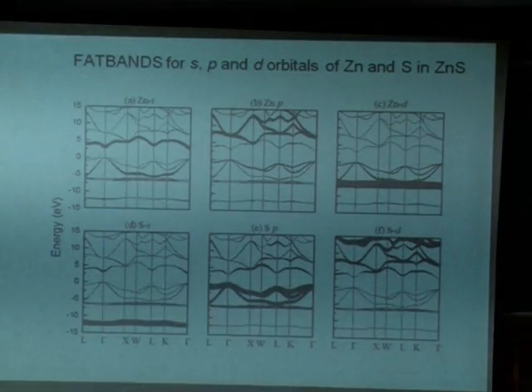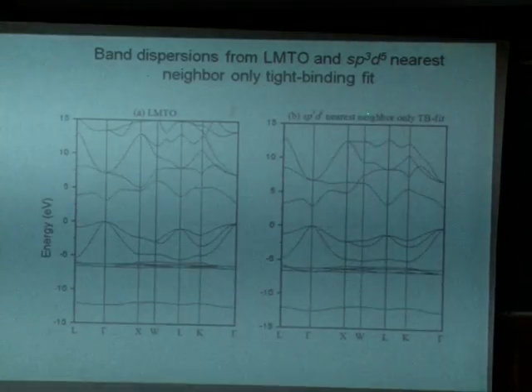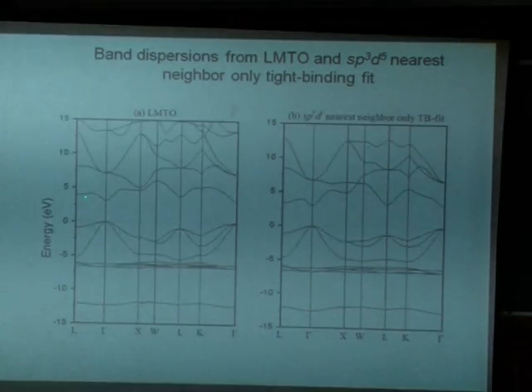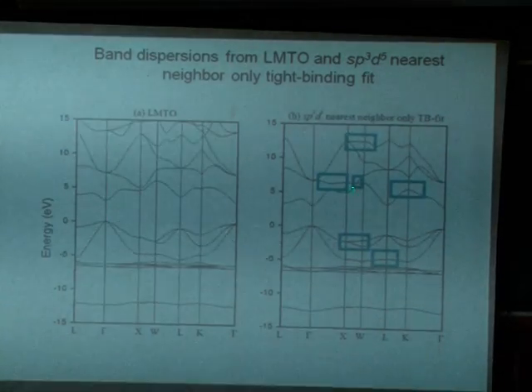And then we calculate how it looks. It turns out that the best sp3d5 fitting is here. Now you see the D states in the tight binding coming up because I have included the D level. And you can see that it has improved. But there are still some places where things are not good. For example, here we have this big dip, it is very flat. Here it opens up this much, but here it's nearly degenerate in the same place. Here it is flat, here I get a dip. So some of the details are still not good.